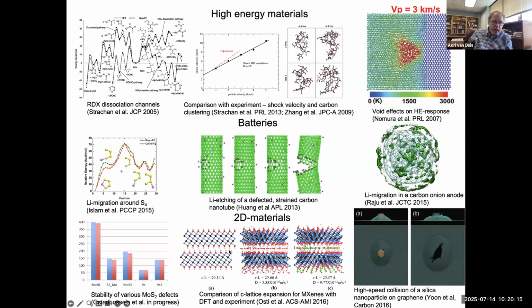A more recent focus in my group has been 2D materials, especially chalcogenides, so molybdenum disulfides, very much structurally similar to graphite. We also worked extensively on MXenes, so in this case these are titanium carbides, but it can work with many different transition metals. So we had collaboration with Yury Gogotsi's group at Drexel, where we developed many different MXene potentials.